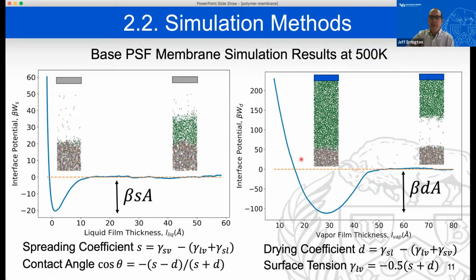We also do another form of the simulation in which we do a so-called drying simulation. So for the drying simulations, we look at the growth of a thin vapor phase in the vicinity of the surface. In this case, the mother liquid, if you will, or the mother fluid, is the liquid phase. And so we're growing a thin vapor film from the surface, and we're looking at what happens to the free energy during that growth process.